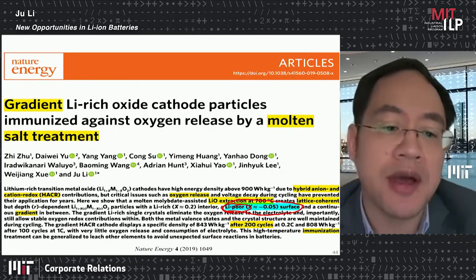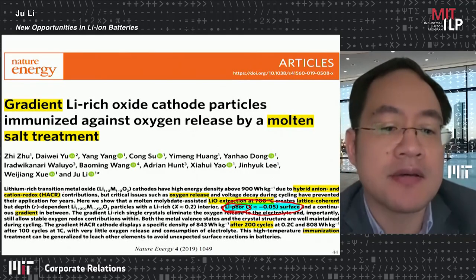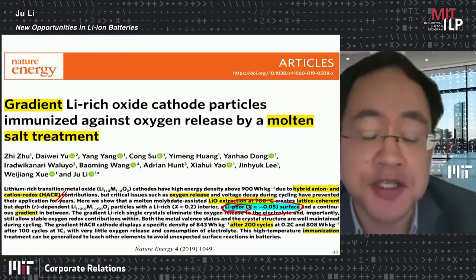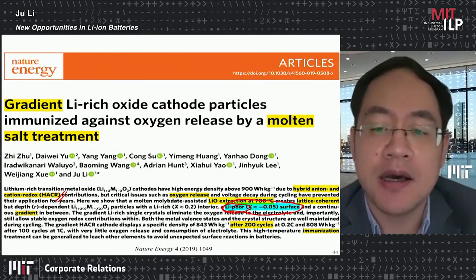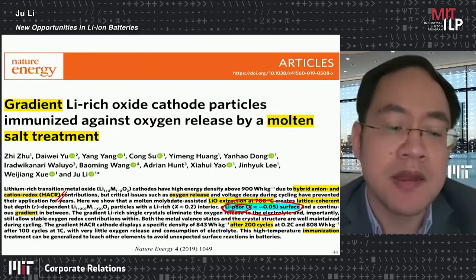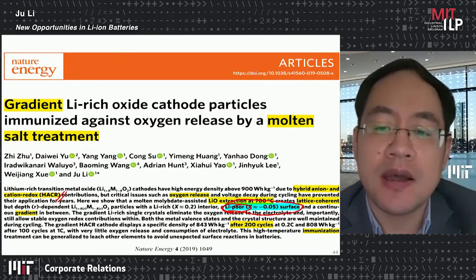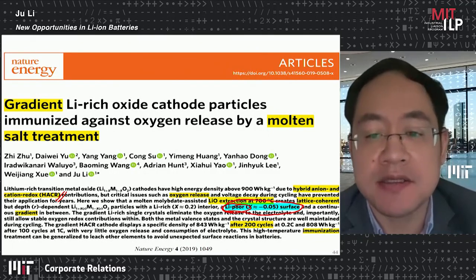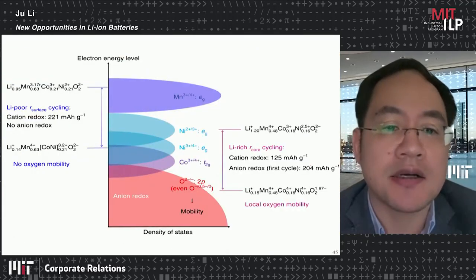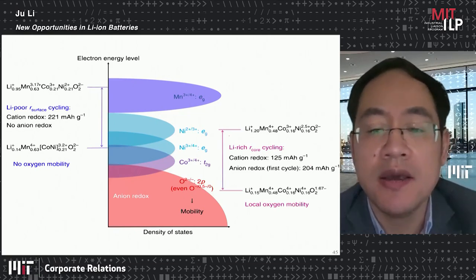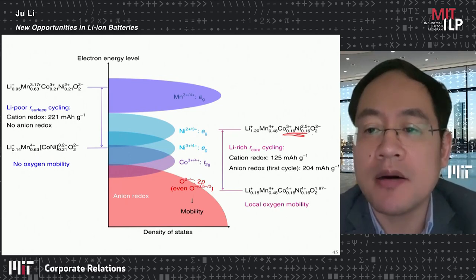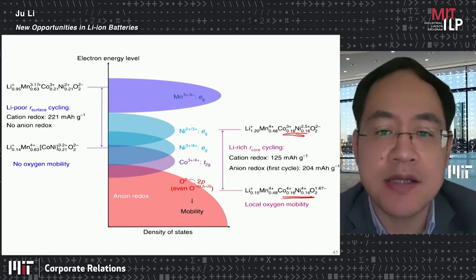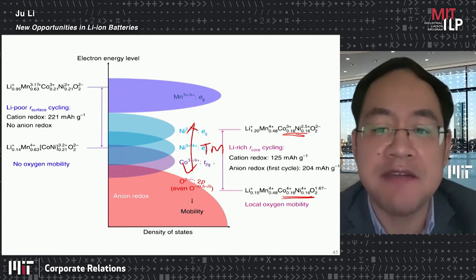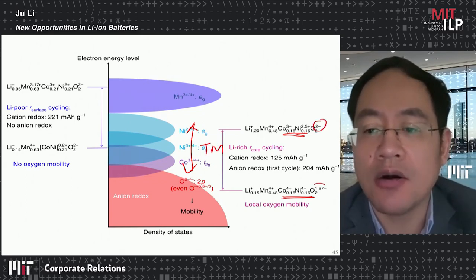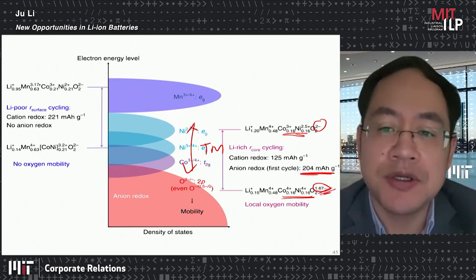And in the core, you're still going to have local oxygen mobility because we think that is just unavoidable if you try to use oxygen's intrinsic capacity. But we try to shut off the global oxygen migration by modifying the surface. And the way we do that, so this is the band diagram. In the core, we're going to use these cobalt and nickel redox capacity. So these are transition metal redox, which are safe assets. But we're also going to use oxygen redox quite significantly, actually contributes theoretically up to this much contribution.